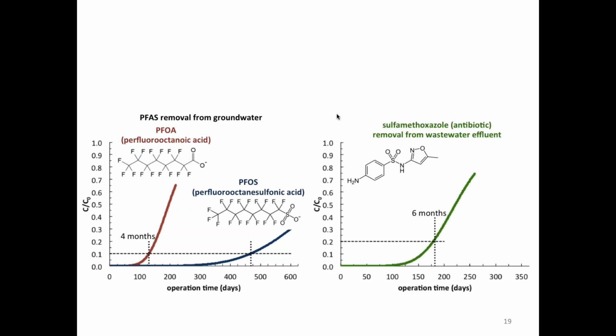And then a final example: sulfamethoxazole is a human and livestock antibiotic, very commonly used, also very difficult to remove by adsorption. It's commonly found in wastewater effluent. This simulation suggests that if your treatment goal is to get 80% or better sulfamethoxazole removal from a wastewater effluent, or from a surface water impacted by a wastewater or sewage release, a 6-month biochar change-out time would be a better choice than, say, a year or longer, because sulfamethoxazole is difficult to remove, and because wastewater organic matter is very effective at fouling adsorbents and reducing their adsorption capacity.